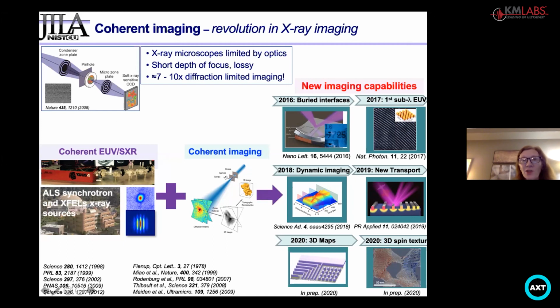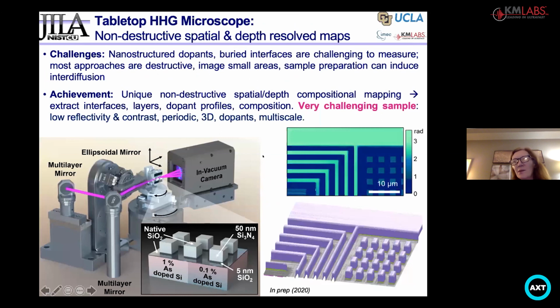These are very challenging to make with high fidelity, but by shining the high harmonic beams on a material and then analyzing the scatter pattern, we can look at buried interfaces. We've achieved the first subwavelength imaging. We can do dynamic imaging, look at energy flow. And the thing I would like to talk about, for one slide, is a non-destructive approach for making a 3D map of a material with composition, layer structure, and interfacial information.